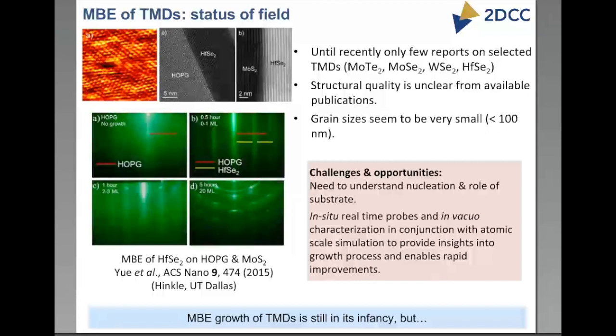This is an example of work from Hinkle at UT Dallas, showing some in situ STM measurements, ex situ transmission electron microscopy, as well as RHEED measurements. Clearly, having these in situ real-time probes is going to be very important to try to understand how the growth can be improved and to understand the details of the nucleation and the growth kinetics.